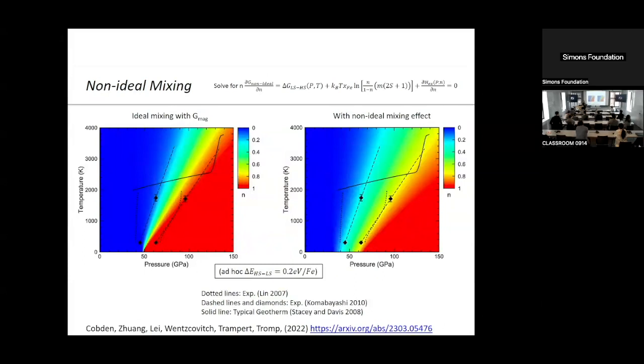It is not. You can do a calculation of the excess free energy, how the energy changes when you change high spin, low spin configurations for the same low spin fraction. There is an effect. It's a small energy difference between different configurations, but when you're talking about delta H equal to 0, any small change is significant. So you can broaden this mixed spin region by going beyond ideal solid solutions.